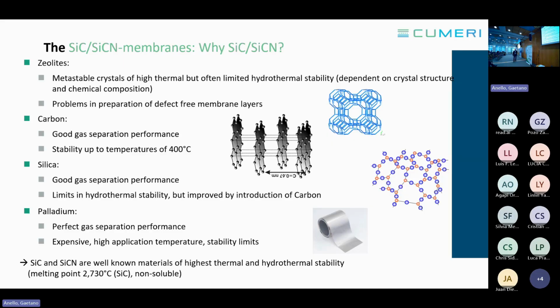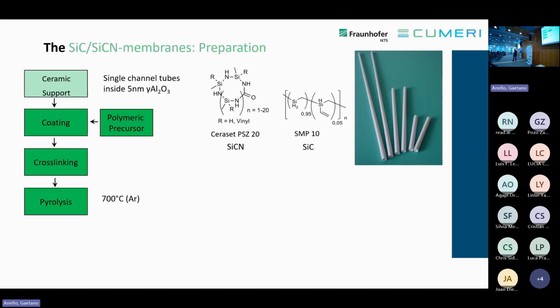So it's an interesting material, but making membranes from them is also very challenging. We started to make such membranes on top of alumina substrates. We used single channel elements with a final supporting layer of gamma alumina with 5 nanometer pore size. Then we coated these tubes inside with commercially available precursors. You can see here, right hand side, one for the production of silicon carbide, and the other one for the production of silicon carbide nitride. Then we had to cross-link them and proceed with pyrolysis in a separate cell in argon, and by doing so, you get the ceramic membrane.